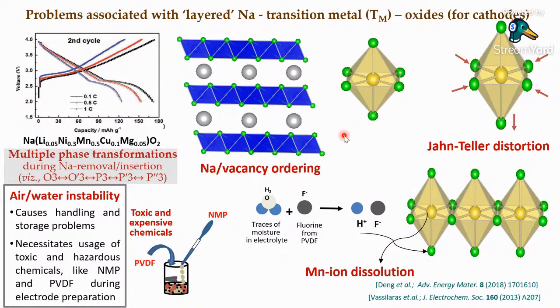So this air-water instability is a problem with handling because one has to minimize the exposure to air, and it also mandates that the electrode preparation, for which a slurry has to be made prior to putting on the current collector, has to be done using something like NMP and PVDF, because water cannot be used to prepare an electrode slurry with these highly hygroscopic cathode active materials. So that is another big problem, because NMP is very toxic and it's not good to use it.